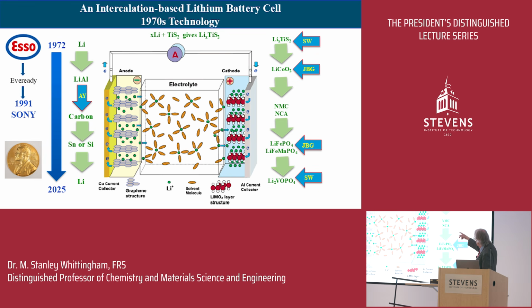And while we started out, the anode was pure metallic lithium. Then we switched to lithium aluminum alloys because lithium makes dendrites, and some people have noticed that. That's what creates some of the fires. Then Akira Yoshino said, lithium aluminum isn't all that good. We can cycle it half a dozen times. He then worked on carbon, which is what I show you here. So these are the sheets of graphite. If you've got a lead pencil, that's what ends up on your piece of paper, those sheets of carbon. So the lithium goes in and out of the carbon.